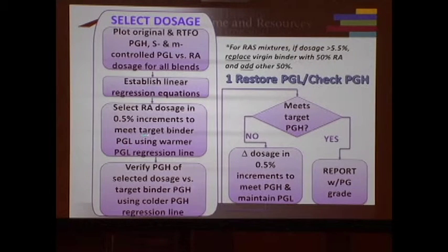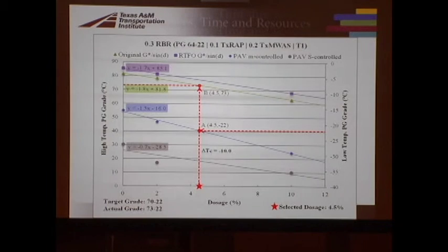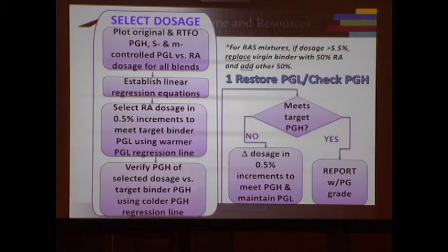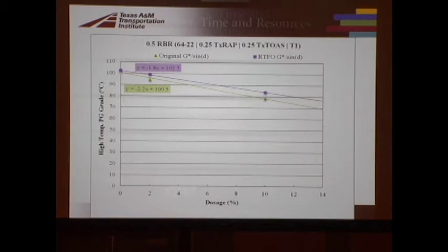So you're of course using the warmer low temperature grade, which was M controlled, and then you're verifying it using the colder high temperature grade, which was the original binder, not the rolling thin film. Okay, so that's the first approach that we tried. And we note the PG, or note the delta TC.